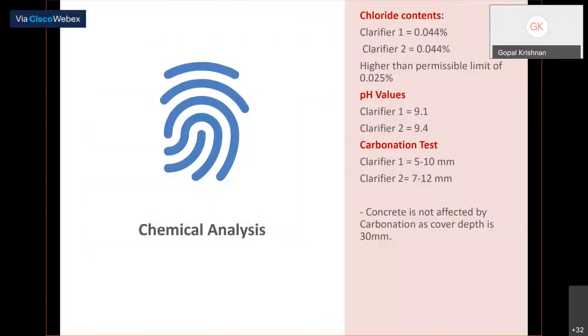It is provided. The chloride is higher than the permissible limit. That's the leaching you can see, and the pH is lowered to less than 10 in some places. Carbonation is 5 to 10 mm from the surface. In one clarifier you can see 7 to 12 mm. So carbonation is not much affected. It's at a very early stage. The cover is adequate. They provided proper protection.